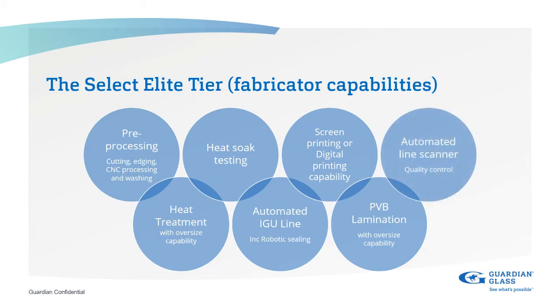And automated line scanner, obviously this is for the quality control, and this will monitor the glass as it exits the furnace. This will monitor the glass for roller wave distortion, edge lift, leading edge and trailing edge requirements. And also, to some extent, the new systems now can also check for anisotropy as well. So all these, as you can see in there, these are actually select elite requirements.